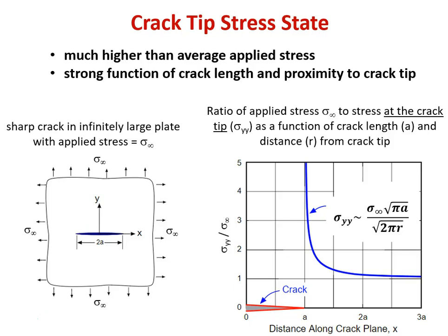So if we're wandering through the material, and we'll move over to the right-hand diagram, you can see the crack position is located down on the x-axis from 0 to a. So the origin of this graph is now kind of centered over the center of the crack. And if we are at any position in the x direction relative to that crack tip, what would be the stress that we would see at our particular location? This is in terms of the ratio of the stress that we would see versus the applied stress on the whole plate. If we're at 3a, way out ahead of the crack, in material that has not cracked yet, we wouldn't really see too much more than the average stress being applied to the plate. We're at about the bulk average.